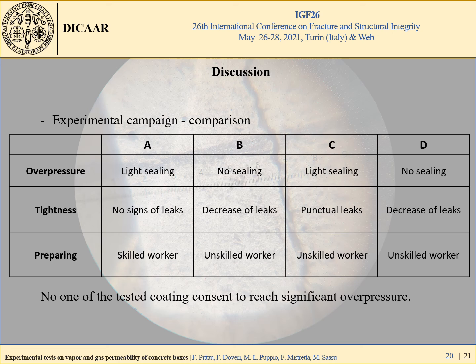The table summarizes the results of the experimental campaign. The best performances in terms of tightness are relative to specimen A and to specimen C. This last can be suggested because of the simple application of the external coating, which required unskilled workers. Although none of the specimens allowed an overpressure, this result can be attributed to the very severe test conditions.